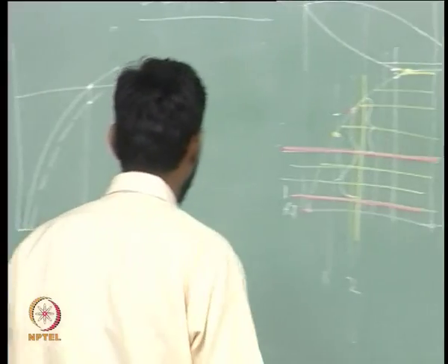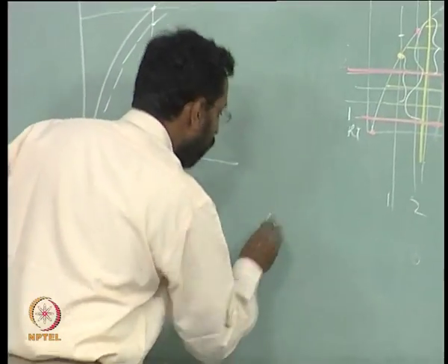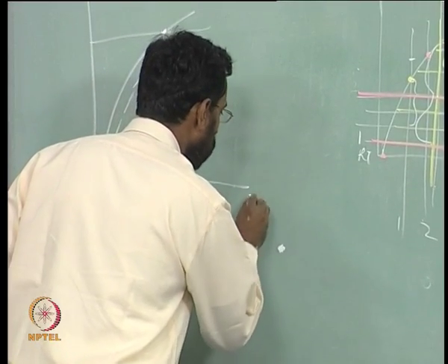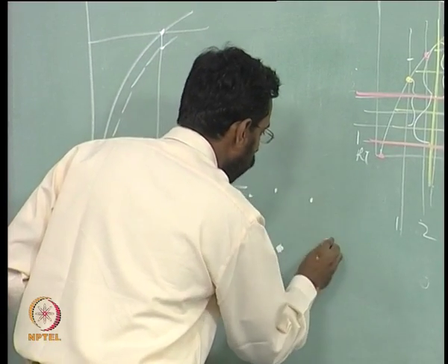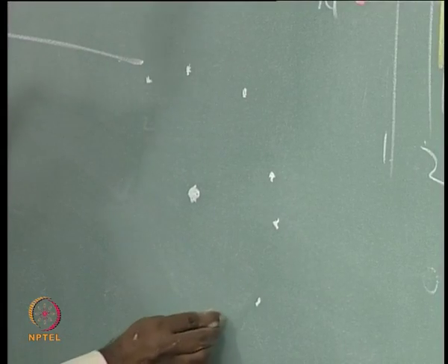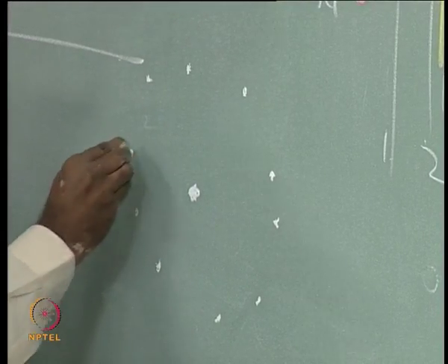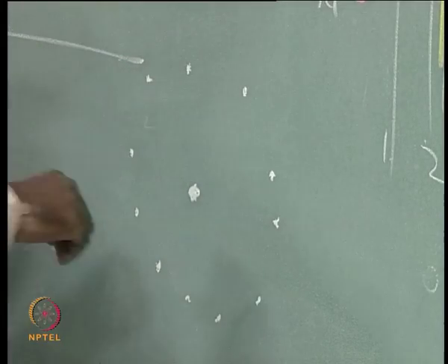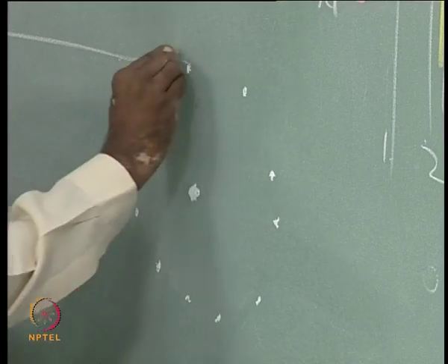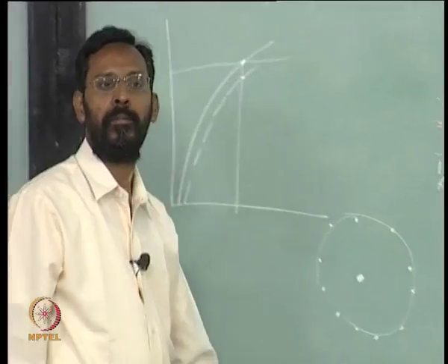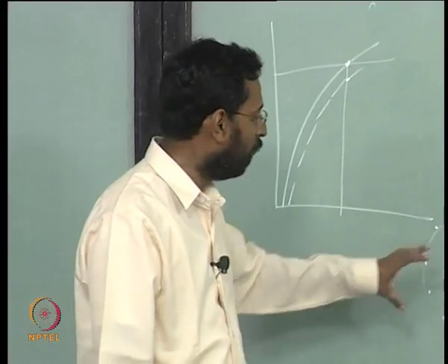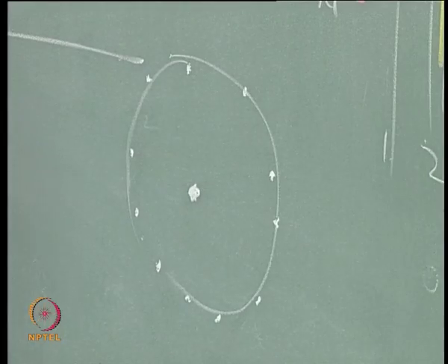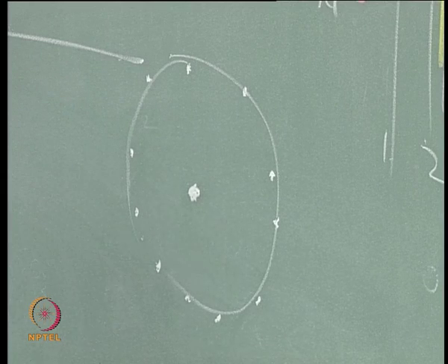So the diffraction pattern looked like this, a central spot with some 10 spots around it, equidistant. So 10 spots on a circular ring, let us say, which actually looks like a 10-fold, and if you know a little more crystallography, you can know how to differentiate between a 10-fold and a 5-fold.